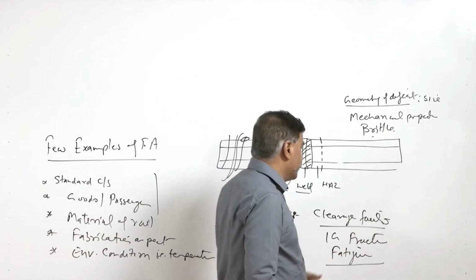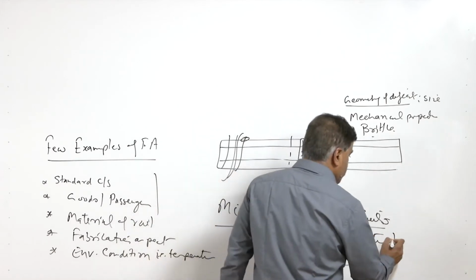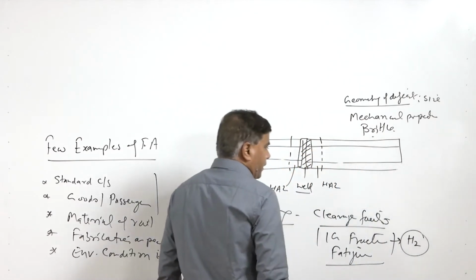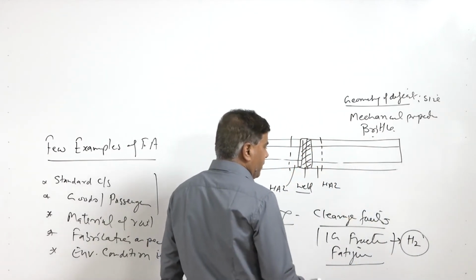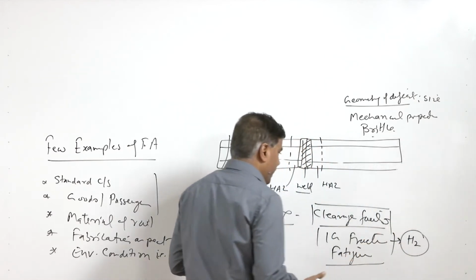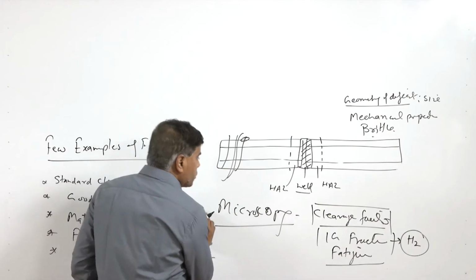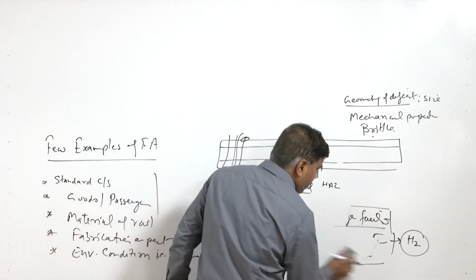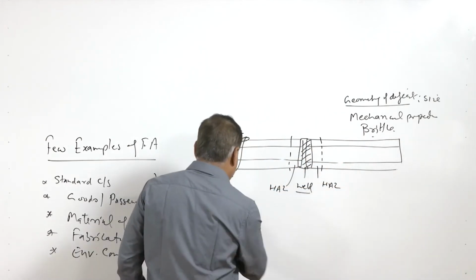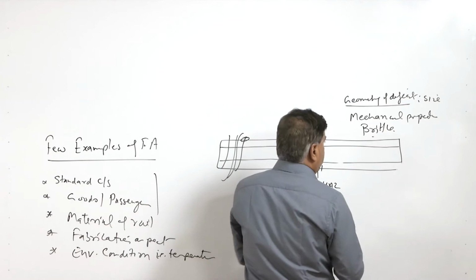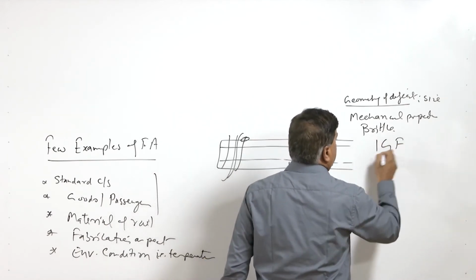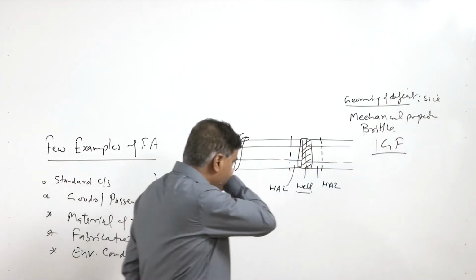If there is intergranular fracture, then it will present the possibility of the source of the cracking, like hydrogen embrittlement or hydrogen induced cracking, or if there are just simple cleavage facets, then this is an overload fracture. So, microscopy will reveal these microscopic fracture mechanisms, and accordingly this will be used as a basis for the analysis subsequently. Say if it has revealed intragranular fracture, then that also will be recorded.